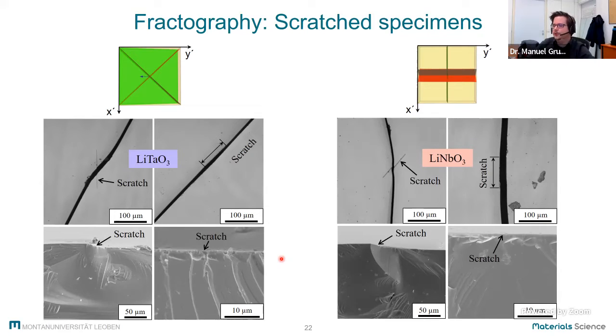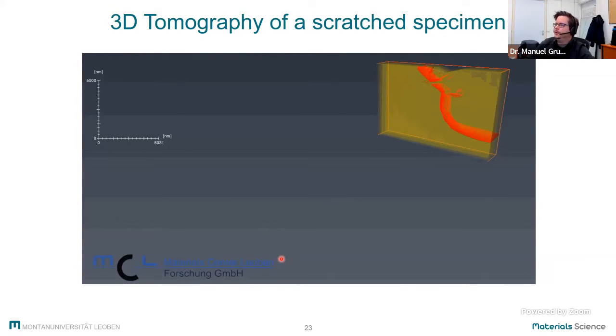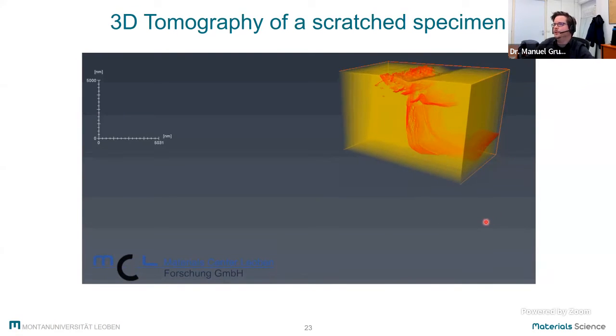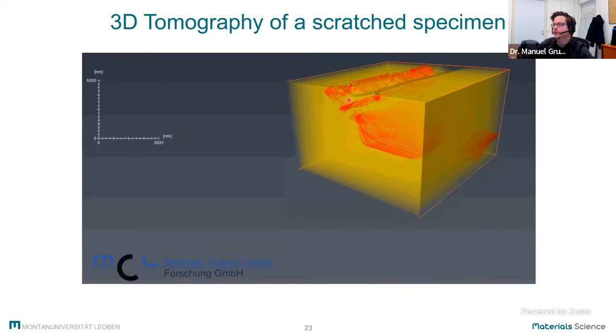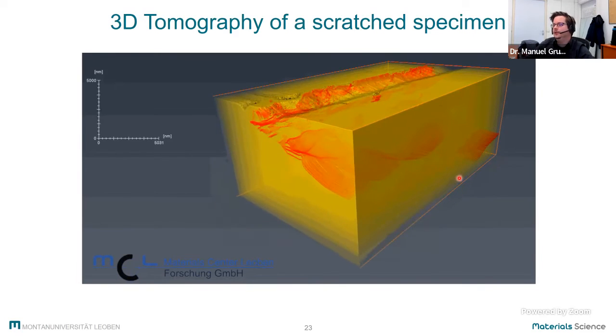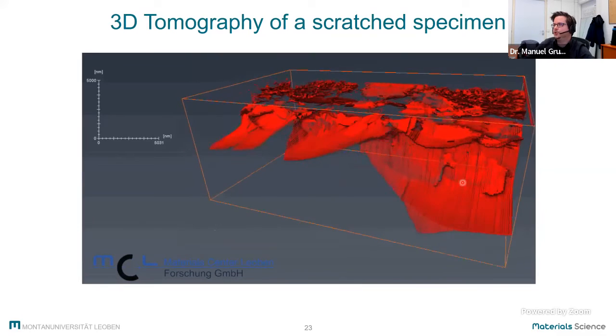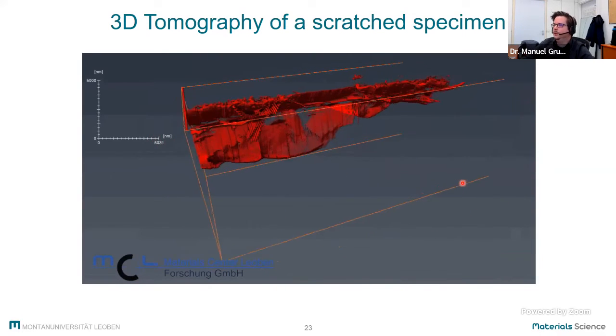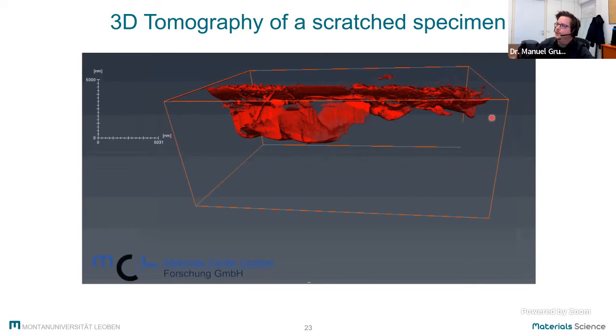And the reason for the large scatter in data, even though we had very controlled testing conditions and always the same load, we can see here in this 3D tomography, where you can see on top the induced scratch with our nanoindentor and the 3D network of the subsurface damage. And if we exactly stop at this point, we can see that we can have relatively shallow subsurface damage in this region, deep subsurface damage in this region, and this can explain the large scatter in data. So even for the same load and the same scratching direction, we get a lot of differences in severity of the induced damage, and this can explain the large scatter in strength data we will probably not overcome even for mirror polished specimens. So to summarize this